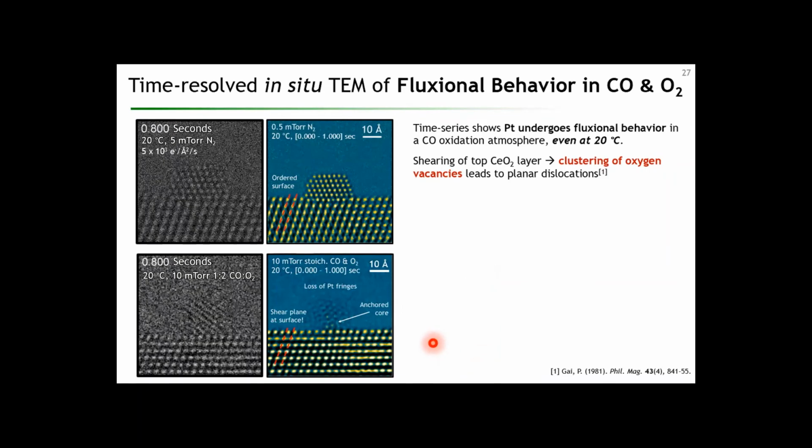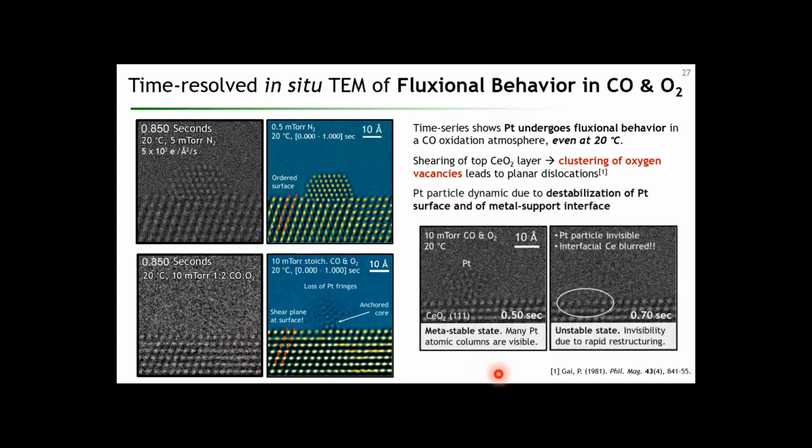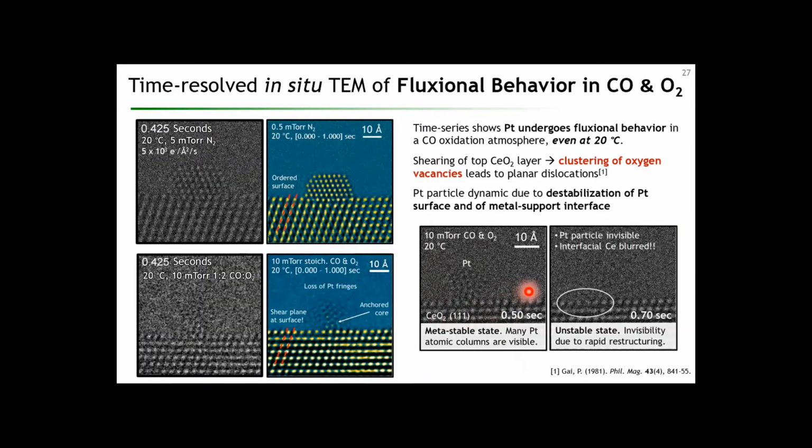And then if we want to understand what's happening here, we have to begin to understand what structures are occurring in these different environments over time and be able to describe them. So here's just one highlight of that effort. I'm summing the time series to 100 milliseconds time resolution. It was taken at 40 frames per second, and now we're summing it to 10 frames per second. And in this case, you can see that there is a moment of relative stability or metastability for the nanoparticle, even though it's only a couple hundredths of a second.